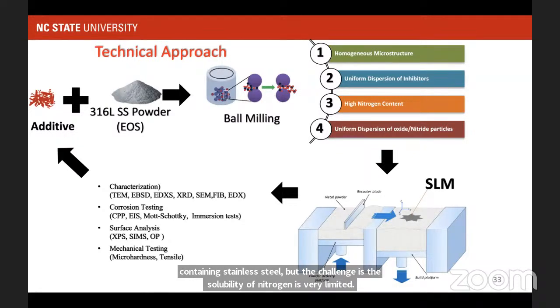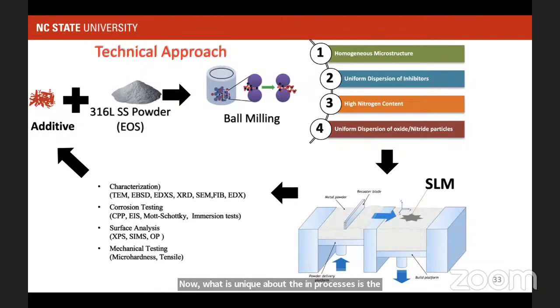Now what is unique about the AM processes is the temperature goes very high, and the solidification rates can be very high. It could be like 10 to the power 7 Kelvin per second. So huge solidification rate, so you can dissolve that nitrogen in the material, and then you can retain it too. So we had thought of a high nitrogen containing, more uniform microstructure, and then we learned that actually you don't necessarily need a uniform microstructure and all that.